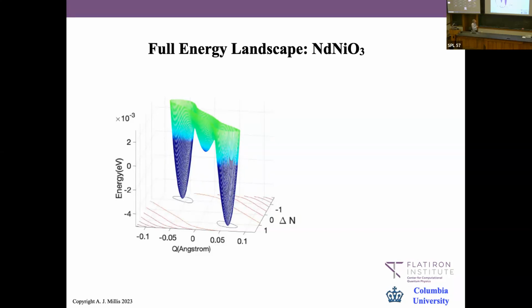where you have a minimum at zero lattice distortion and zero electronic distortion, which is locally stable. You have another minimum, well, two, because they're related by symmetry — you have to choose which sublattice gets it — which involves both an electronic and a lattice distortion, and nothing else in between. This minimum is locally stable. There is no minimum with lattice only and no electronic distortion. There is no minimum with electronic distortion and no lattice distortion, right? So in this compound, the electronic and lattice degrees of freedom are inextricably coupled, and the transition is driven neither by one nor the other.